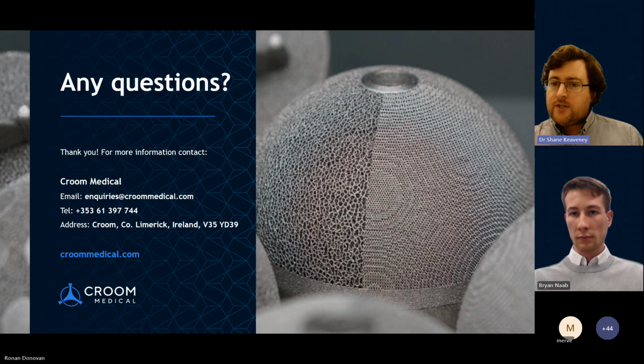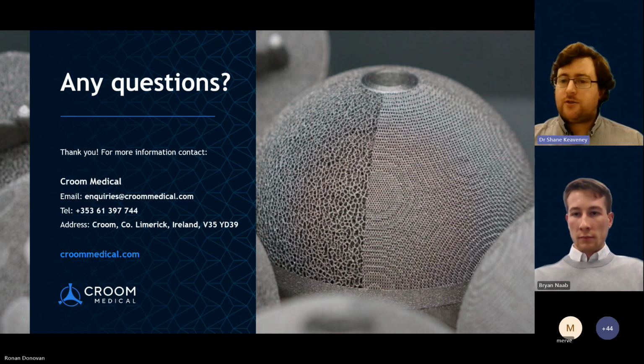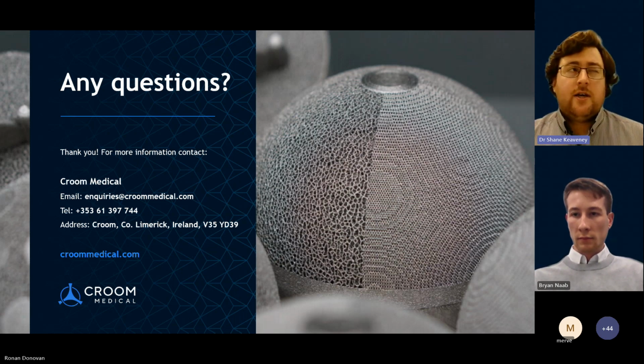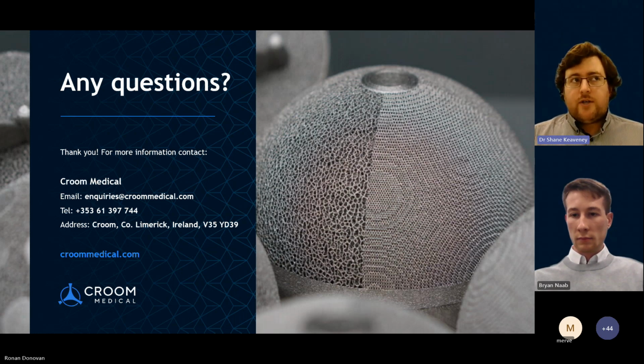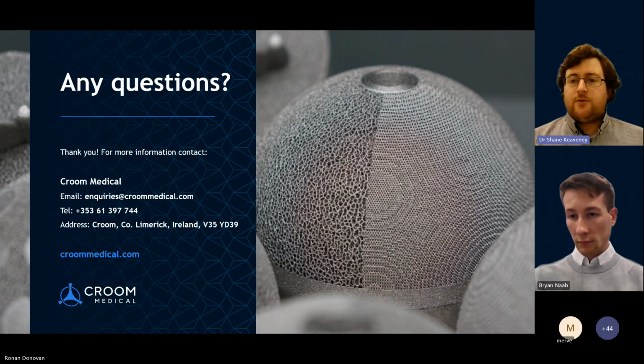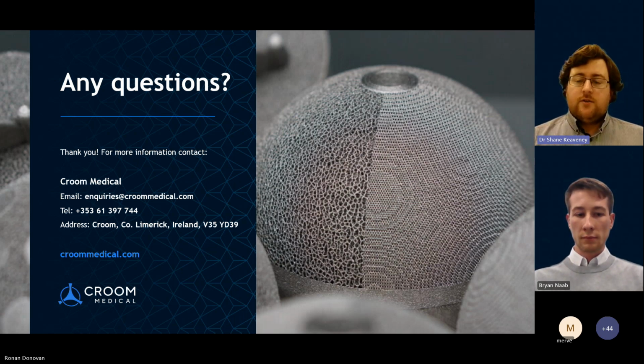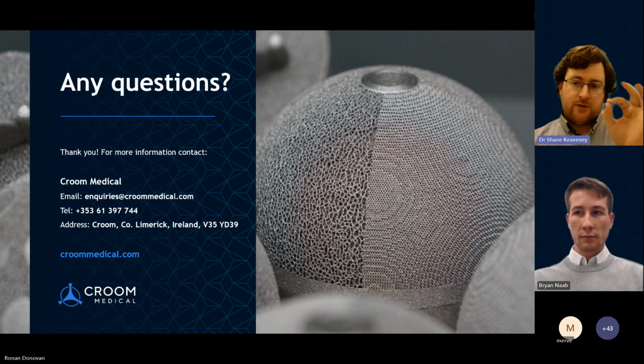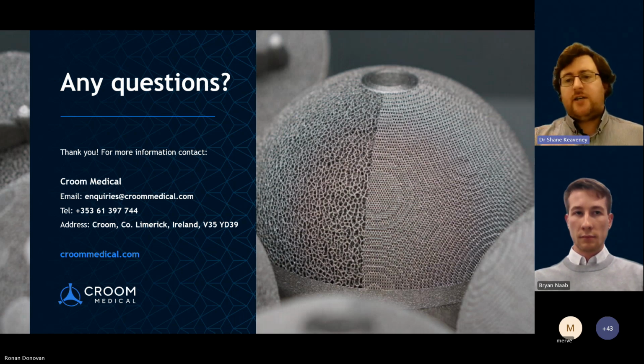There was also another question regarding the additive manufacturing of porous structures, the typical deviation between as-built and as-modeled structures, and how can we minimize it? Well, I might take that one. It's quite an interesting question, because there's a number of different methods for us to make lattice structures, depending on the technology we're using. If we look at the Renishaw system, the one we have here, that uses a point exposure method. So with that, we do not actually model a size for our lattice. The size of the lattice is controlled by the printing parameters. So we have a known input energy versus output size for the lattice. And we work with just the center point of the lattice as our design space, we'll call it.